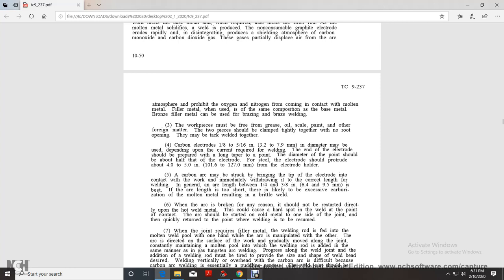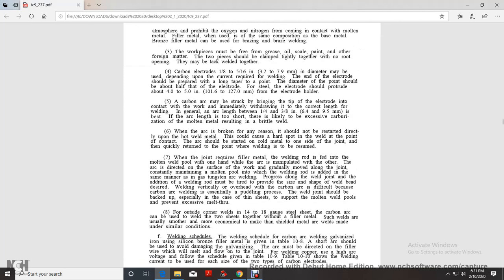A carbon arc may be struck by bringing the tip of the electrode into contact with the work and immediately withdrawing it to the correct length for welding. The general arc length is between 1/4 and 3/8 of an inch. If the arc length is too short, there is likely to be excessive carbonization of the molten metal, resulting in a brittle weld. When the arc is broken for any reason, it should not be restarted directly on the hot weld metal. This could cause a hard spot in the weld at the joint. Instead, the arc should be started on cold metal on one side of the joint and then quickly returned to the point where welding is to be resumed.